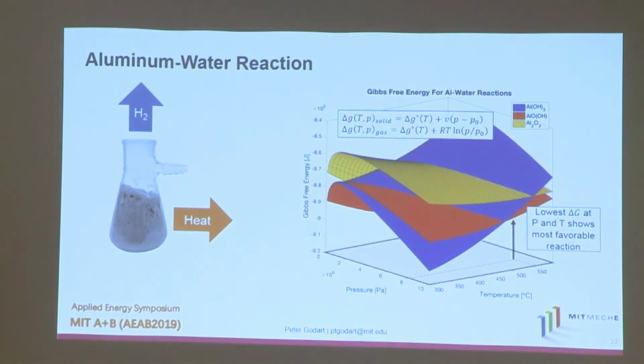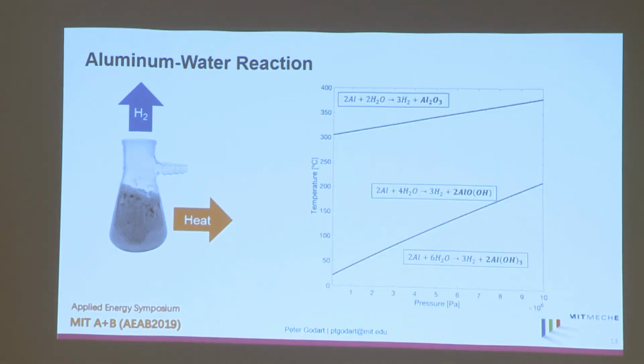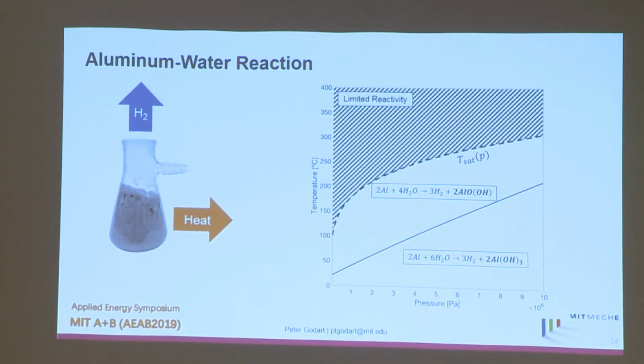We can then project these Gibbs free energy surfaces down onto that temperature pressure plane and plot the intersections. And that gives us a nice map of where on this pressure temperature plane the different reactions are most likely to proceed. We can simplify this a little bit further because we observed that this type of fuel, this type of aluminum activated in this manner does not react well with high temperature steam. And so above the saturation curve of water at these pressures, we've noticed limited reactivity. So we're really just left with these two regimes here.